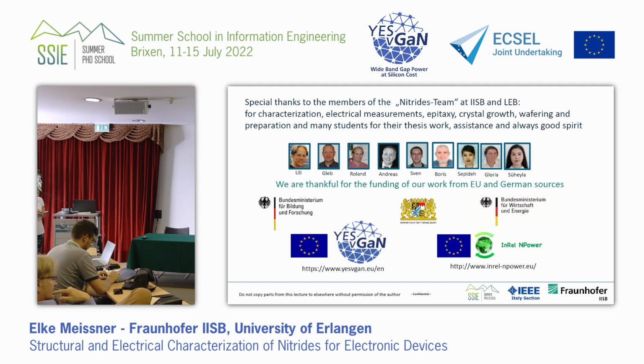If this is a source of the quality where the islands are merging together, is it detectable, for example, by XRD, by rocking curve? Because the merging of the islands might be the source of dislocations. Can we detect the dislocations to determine whether there are any? Because in the further layers we can see it, if further GaN layers, for example, are grown. The further layers will react on what you're doing in the nucleation layer, yes.